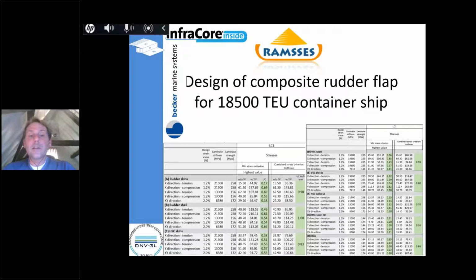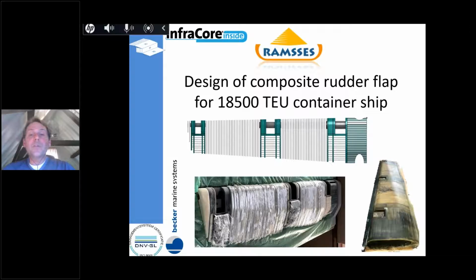You see that we tuned it so that the rudder shell is on 1 because the goal was to make it as lightweight as possible. So the design requirements were met. And what you see on the upper figure is, I think, a good illustration of the flexibility that our technology enables. I said a couple of minutes ago that we place webs in the direction as deemed necessary. So you see webs running in horizontal direction, vertical direction. You see these green areas, that's where solid blocks are placed because those are the higher stress and strain areas. So we wanted to have additional flesh there. So we just place the material where needed and in the direction as needed.